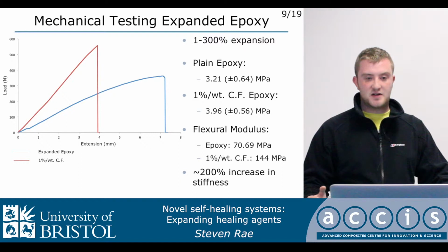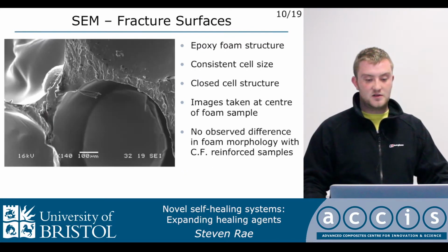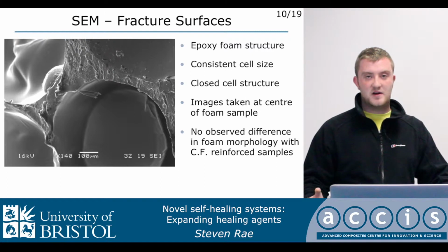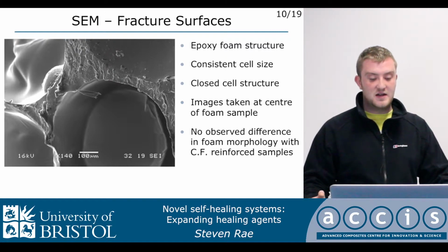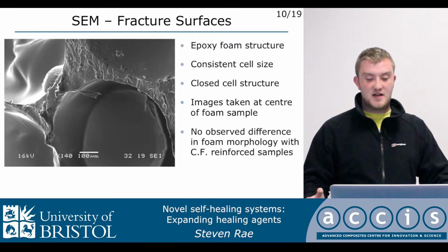As you can see from the figures in the slides, we get a significant increase in the material properties by including the carbon fibre in there. So to investigate what was going on when we tested these samples to failure, we've done some SEM analysis of the fracture surfaces and to characterise the foam itself. And each time we saw a regular, consistent cell size, and also it was a closed cell structure, and incorporating the carbon fibre in there had no influence on the morphology.